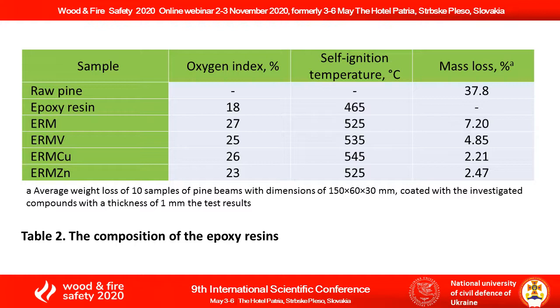In addition, the self-ignition temperature of fire retardant coatings with various contents of modifying additives was determined according to ISO 871-2006. The tests were carried out according to standard methods. To determine the self-ignition temperature, samples of epoxy composition weighing 3 grams were used. The research results are presented in Table 2.